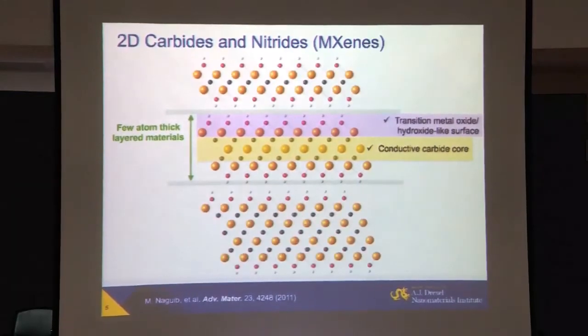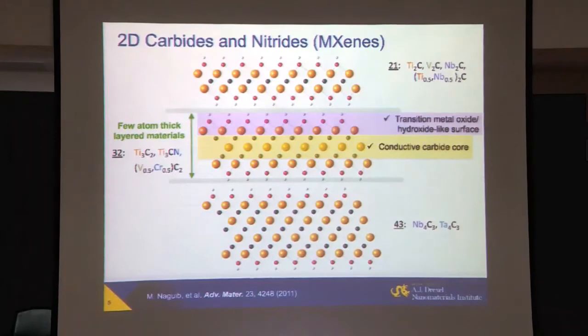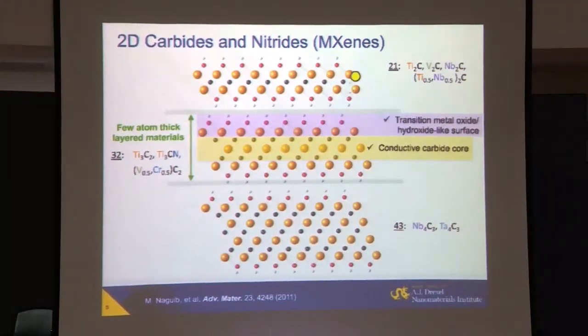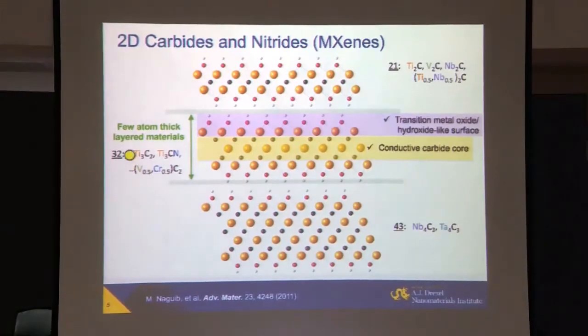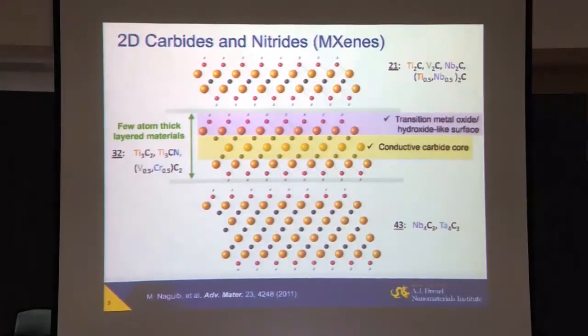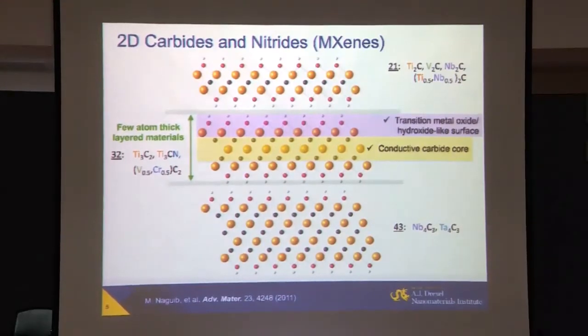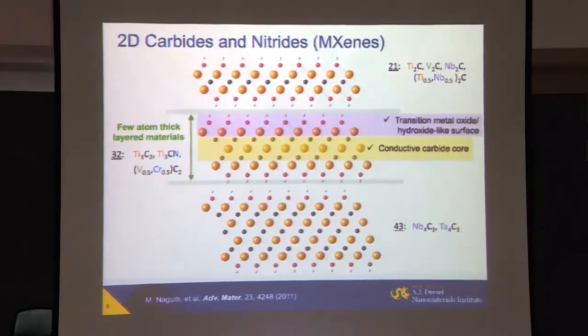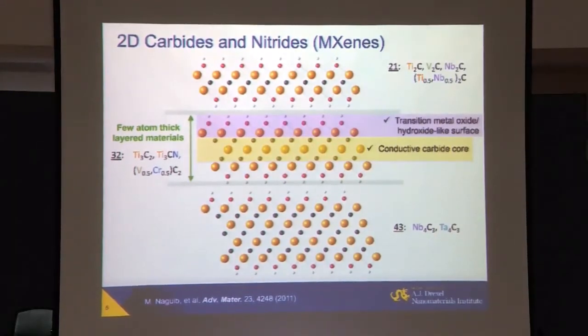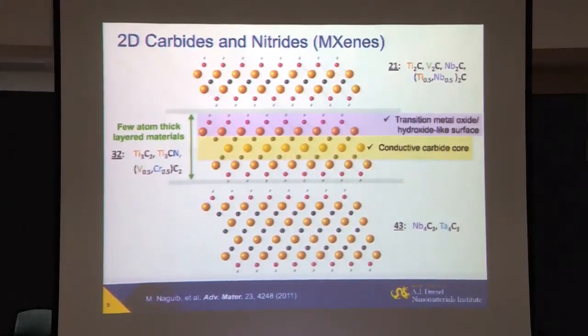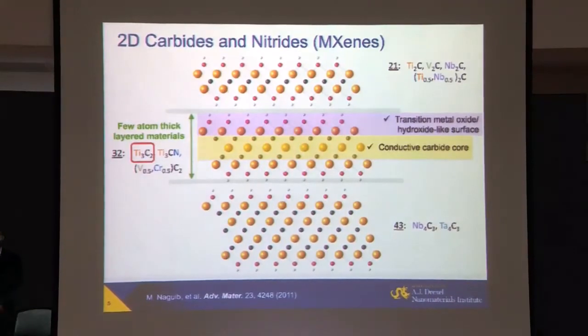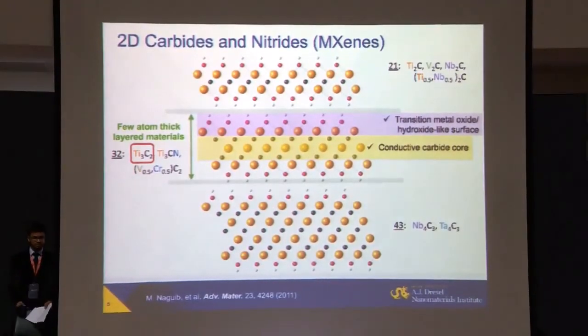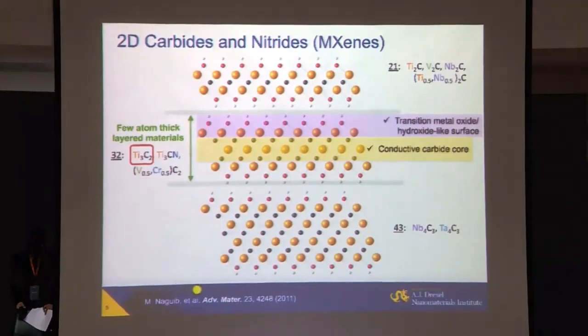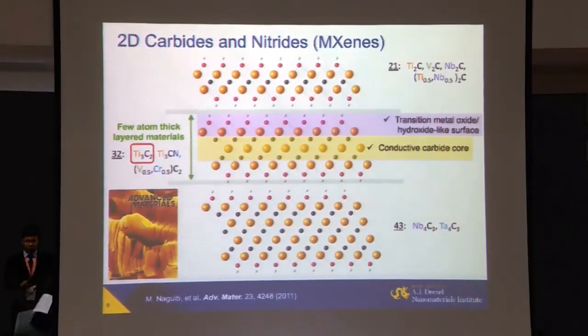What is also interesting, there are three common groups, three flavors. We call them M2X structures because of 2 atoms of transition metal and 1 layer of carbon or nitrogen, M3X2, M4X3 structures here. So what does MXene mean? M stands for transition metal, X is carbon or nitrogen, and the ending, initially taken from graphene in organic chemistry, is now used simply to show two-dimensionality, like borophene, silicene, germanene, and other materials here. Titanium carbide Ti3C2 was the first one that Michael Naguib discovered, at the end of 2010, and we published this paper in Advanced Materials in 2011. This is the cover of this first article.